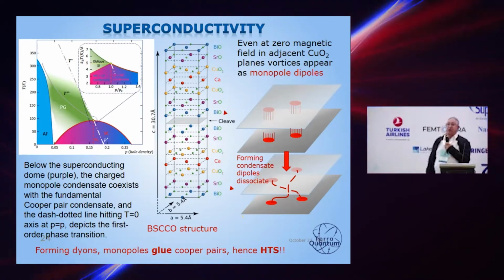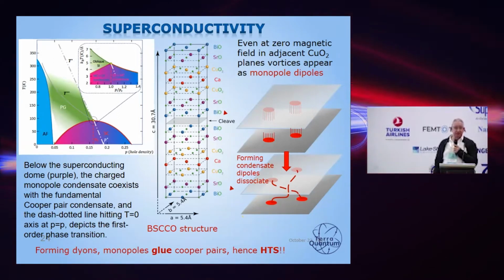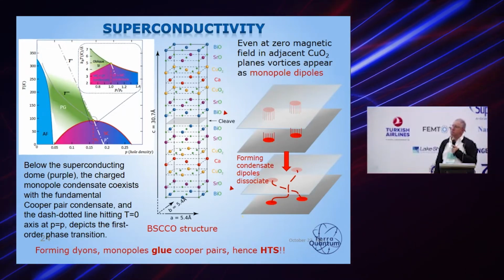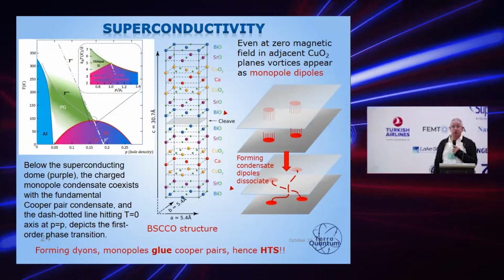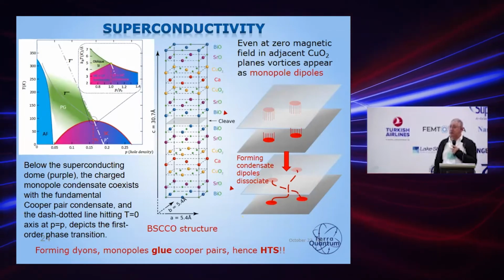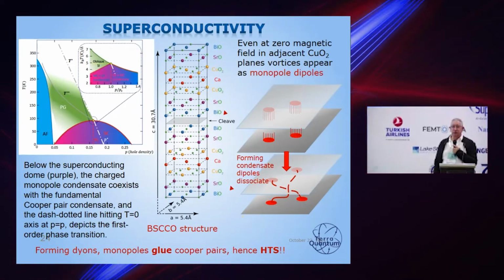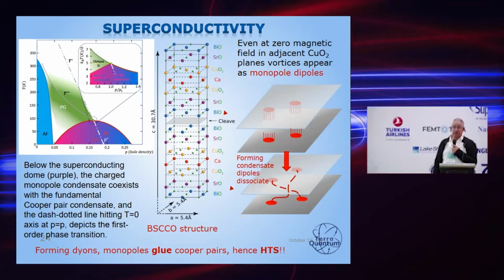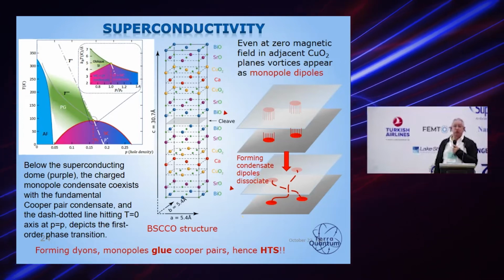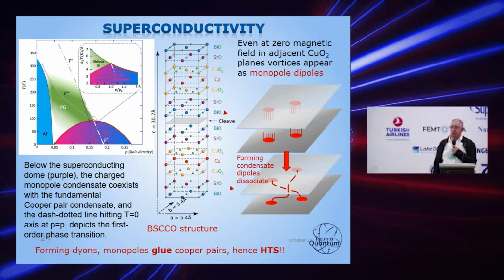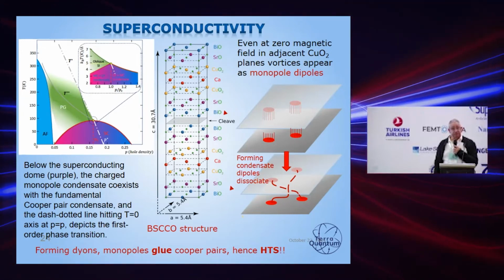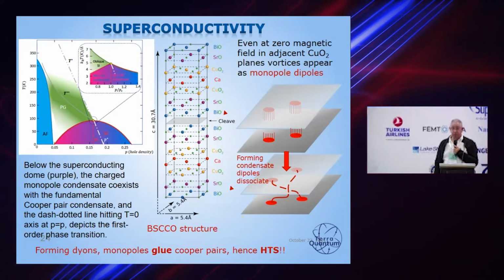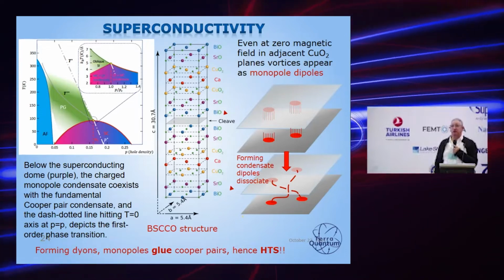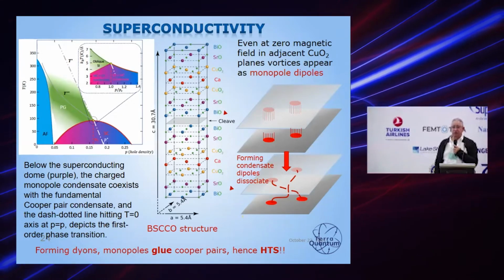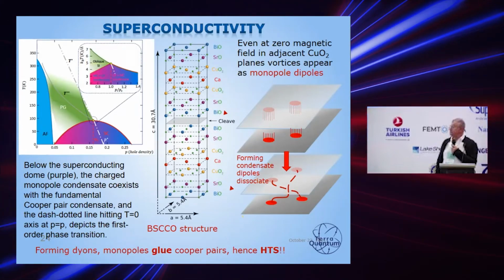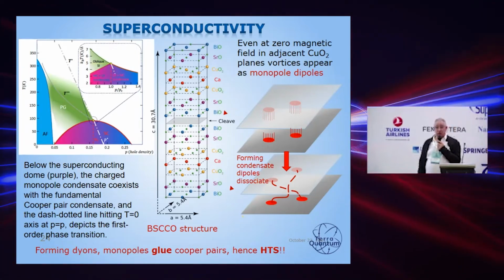Okay, now, one small detail. We know pretty well that in all these layered materials, if we study some microscopic effect, like the Hall effect in the usual high TC superconductors, as measured by usual means, or if we study quantum fluctuations near the superconductor-metal transition or something like that, we see absolutely two-dimensional behavior. This is now probably a subject of textbooks. But at the same time, this monopole-related behavior we were talking about is essentially a three-dimensional feature. Without mentioning monopoles, actually, Ivan Bozovic was mentioning this himself. And this is exactly what we have in our description.